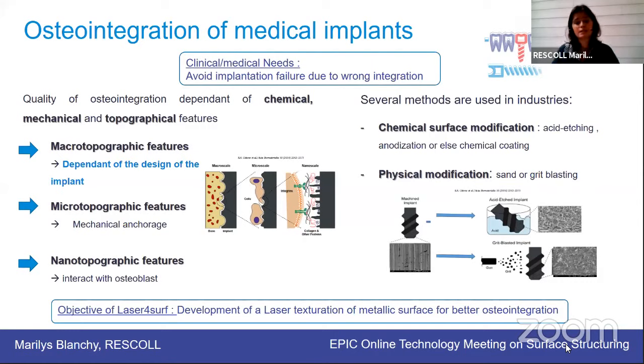So first of all, what is interesting for medical devices to use control of the surface is because there is a failure of implantation from time to time due to the wrong integration of the implants. It's what we call osteointegration. One of the most used materials today for orthopedics, for example, or for dental implants is titanium. So it's a very well-known and extremely biocompatible material. It has excellent corrosion resistance and good mechanical properties, but it is also quite inert towards cell interactions. So in some cases, implants show long-term failures due to insufficient integration toward bones.